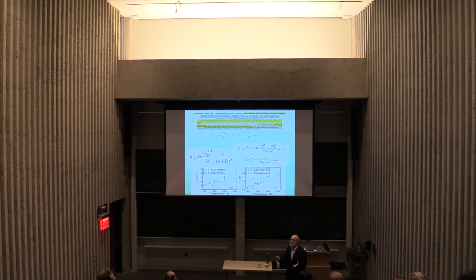It's not like in the standard band theory, where you do your bands and the masses don't depend on temperature. Here, the masses are strong functions of temperature. Furthermore, the 1/τ* has a T² dependence, like we had asserted. So you see, now you start seeing the power of having something which is system-specific, but at the same time looking for concepts, for ideas. And this idea of a hidden Fermi liquid, which is underlying all that, in the sense that the scattering rate is still proportional to T² plus a constant, but where all the electronic structure, all the bands are strongly temperature dependent, is something which allows us to understand the anomalous properties of this system.